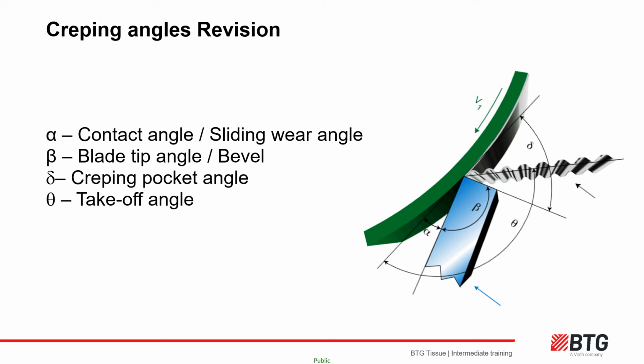This is a slide from the basic training showing the contact angle, also known as the sliding wear angle. This is also close to what we call the blade holder angle. We also see the blade bevel angle, the take-off and creping pocket angles. Increasing the pocket angle increases softness and reduces bulk, and vice versa. When any blade wears, whether it be steel or ceramic, both the tip impact and the sliding wear angle reduce the size of the pocket angle.